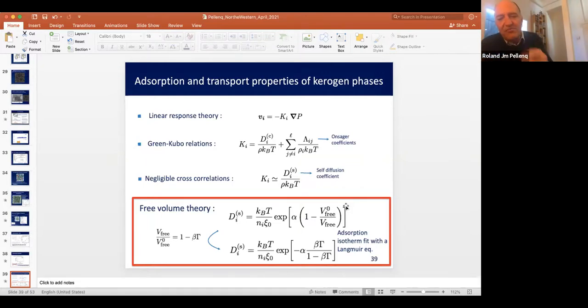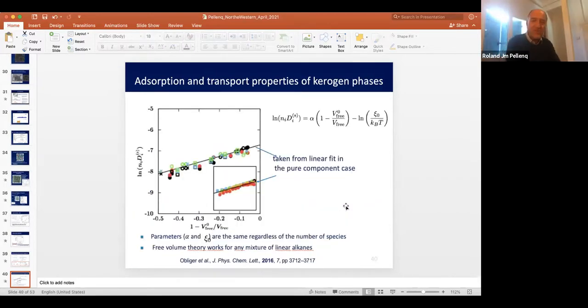Anyway, by knowing the adsorption isotherm, we can predict the self-diffusion coefficient, which equals, because of those nanopores, the transport coefficient. Then we can calculate the K, the permeance, then we can predict the flux. This is very cool, right? So we can predict the flux by just doing an adsorption experiment at equilibrium. All right, does it work?